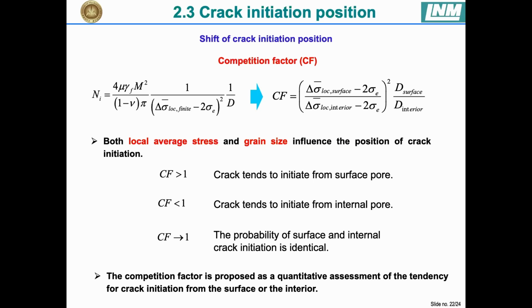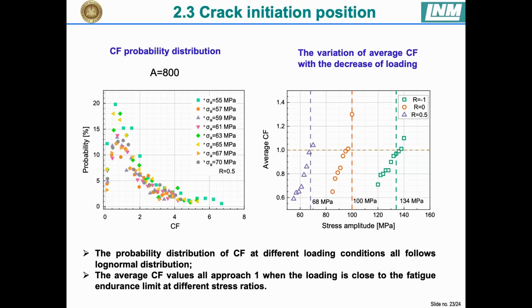When the CF is higher than 1, the crack tends to initiate from the surface pore, and when the CF is lower than 1, the crack tends to initiate from the internal pore. And when CF approaches 1, the probability of surface and internal crack initiation is identical. Also, with A=800, the CF probability distribution can be obtained. The probability distributions of CF at different loading conditions all follow log-normal distributions, and the variation of average CF with the decrease of loading is plotted.